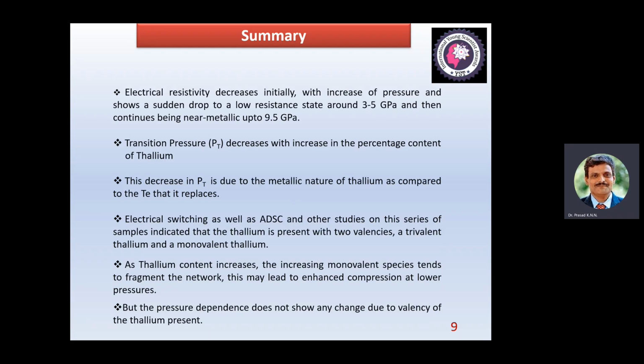With this, what I can summarize as a whole is that the electrical resistivity decreases initially with increase of pressure and shows a sudden drop to a low resistance state around 3 to 5 GPa, and then continues being near metallic up to 9.5 GPa. That is why in the results part of my slides you could see a decrease in resistivity with pressure. The transition pressure decreases with increase in percentage content of thallium. This decrease in transition pressure is attributed to the metallic nature of thallium as compared to the tellurium that it replaces.